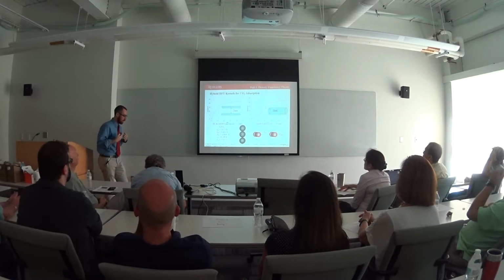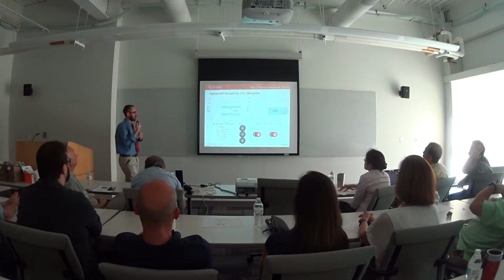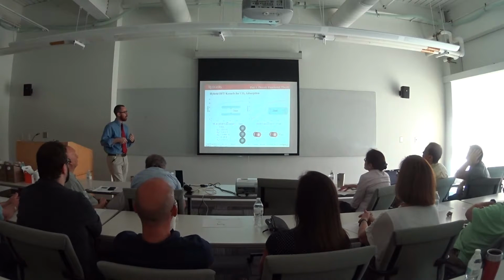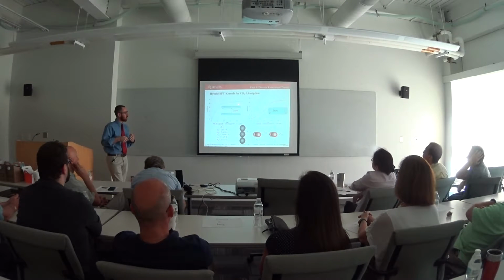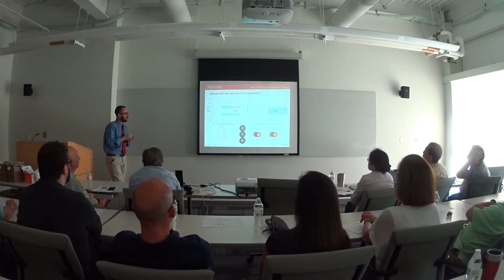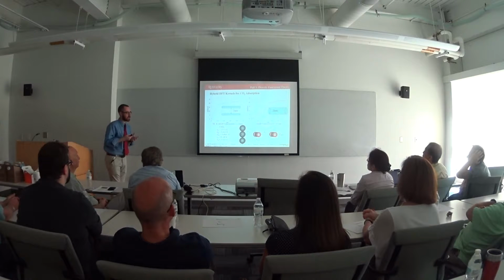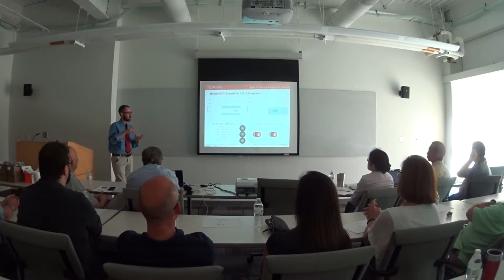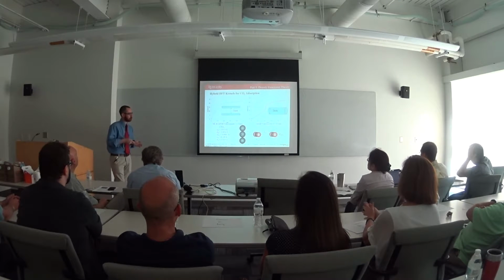So one of the main aspects of this part of the work was developing the kernels. And so for the particular kernels which I'm going to talk about, they have two different pore geometries. For pores which are smaller than 2 nanometers, we use a slit-shaped pore model. And for pores which are larger than 2 nanometers, we use a cylinder. And this is because we're trying to best fit these CMK3 materials, which are roughly cylindrical in their main mesopores, but have slit micropores approximately.